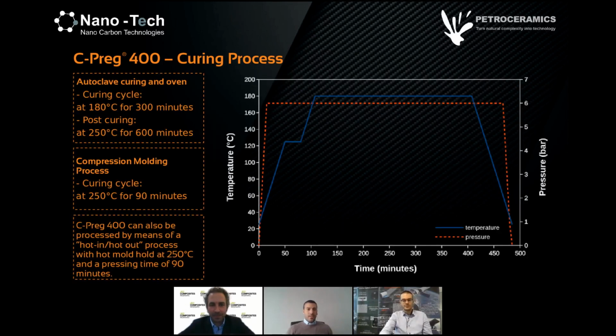Okay, now Andrea. Okay, now let's talk about the curing process. The Cpreg 400 can be cured in autoclave. It has a 5-hour dwell at 180 degrees. And it needs to be post-cured at about 250 degrees for 600 minutes. This is to achieve the maximum TG of the material. The material can also be cured by means of compression molding at 250 degrees for 90 minutes. And then if you want to achieve best properties, you should perform the same post-curing cycle.